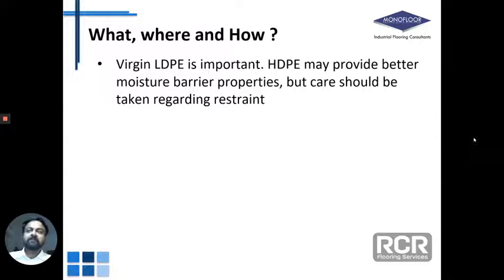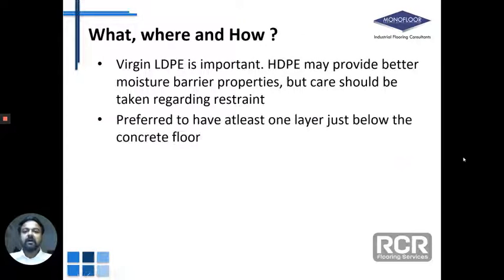HDPE may sometimes provide an advantage when it comes to the contribution it has to vapor barrier, but it may not always be advantageous when it comes to laying them and taking advantage of the slip membrane performance. It's preferred to have at least one layer, and this one layer has to be just below the floor. Whether it's a subbase, a lean concrete or a PCC, a plastic sheet has to be added just below the concrete layer.